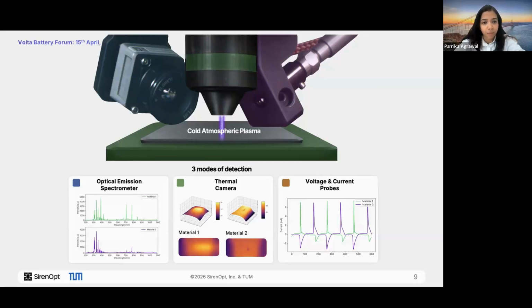So on the bottom panel, you see examples of the three kinds of data that we are collecting. In the optical emission spectrometer data, we are collecting several peaks of different wavelengths, and we monitor how the intensities of these peaks are changing as plasma traverses over the material. The thermal camera captures how heat is propagating through the material surface as it is being heated up by the plasma. And the voltage and current probes measure current going through the sample. For every single measurement point, we apply close to 200 electrical waveforms, and those measure a very rich data set coming from the material itself. So that correlates directly with the material's electrical properties.